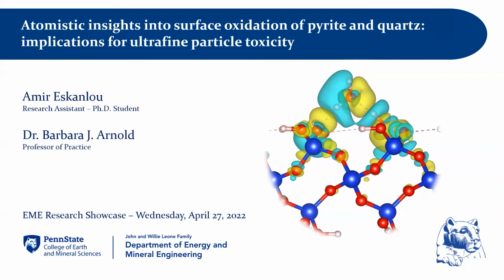So these are our conclusions for this study. You can see from here that on the surface of pyrite, whenever we have oxygen, the oxidation state of iron changes from ferrous iron to ferric iron. And the production of this ferric iron entails the formation of these free radicals on the surface. This shows the importance of oxygen interaction with the surface of pyrite and the contribution of oxygen as an oxidant.